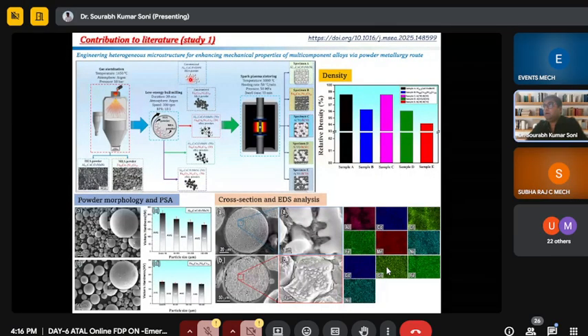In the first work, we prepared some high entropy alloy powder, this is aluminum Cantor, and this is the medium entropy alloy, Fe based medium entropy alloy. These two powders I prepared by the gas atomization process. You can see the very spherical powders we prepared, and further we performed the ball milling operation followed by SPS.